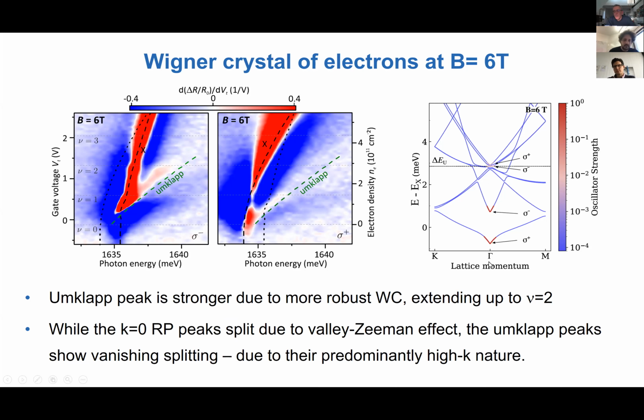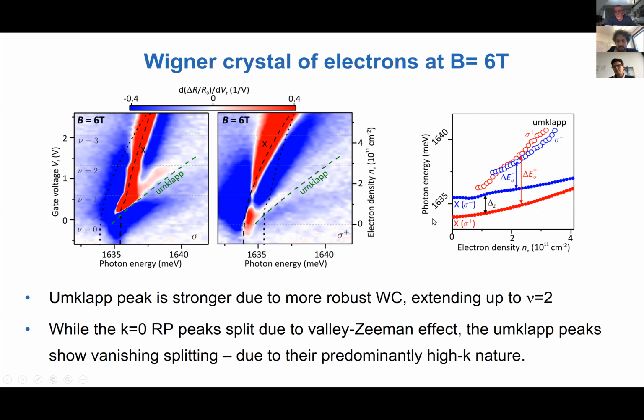Whereas the K equals 0 excitons are subject to the valley-Zeeman effect, which leads to a sizable splitting on the order of a milli-electron volt. And this in turn basically means that the sigma minus can mix much better with the K equals 0 as compared to the sigma plus, and this is the difference that we see here. This is also what we see in the presence of a magnetic field: there is a Zeeman splitting of the main exciton peak, but for the umklapp resonances there is some splitting, but this is all within the error margin, and actually it would be interesting to understand the nature and the strength of this.